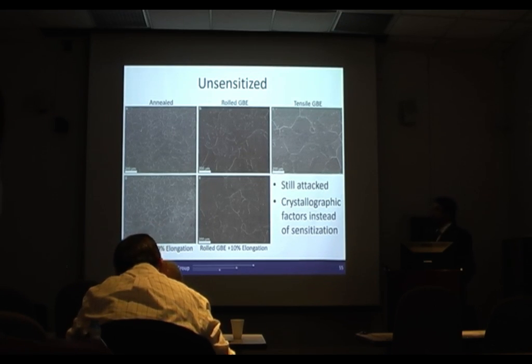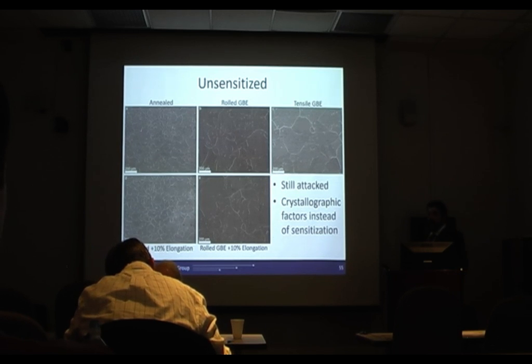And we have our annealed, rolled, and tensile GB again, but we've also added two conditions, the annealed and rolled plus 10% elongation. And we made tensile samples from these microstructures and pulled them. And the idea is, as we're sensitizing these, we want to see the role that adding strain to the microstructures plays.